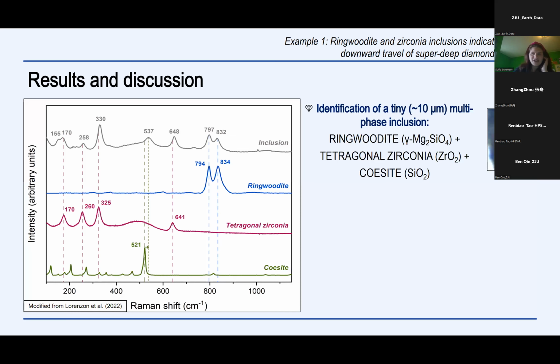Starting with the results from the micro-Raman spectroscopy, it allowed us to detect a very tiny and very unusual multi-phase inclusion. That is the main result that we obtained in this study. This multi-phase inclusion is composed of ringwoodite, tetragonal zirconia, and coesite. In this picture, in the grey line, you can see the Raman spectrum of this multi-phase inclusion. But why did this multi-phase inclusion turn out to be important for us, and which kind of information did we obtain from this particular assemblage? Let's start with the ringwoodite.